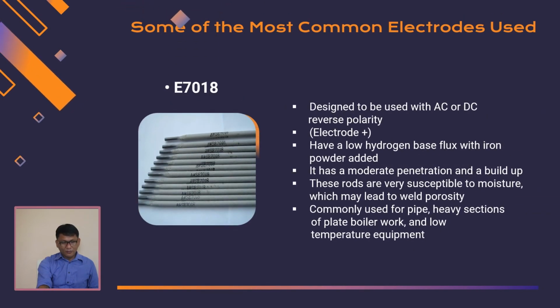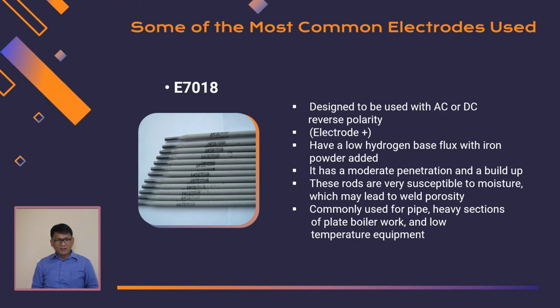Then the last one we have the 7018, designed to be used with AC or DC reverse polarity or electrode positive. They have a low hydrogen base flux with iron powder added. It has a moderate penetration and buildup. These rods are very susceptible to moisture, which may lead to weld porosity, commonly used for pipe, heavy sections of plate, boiler work, and low temperature equipment. So that is the 7018.